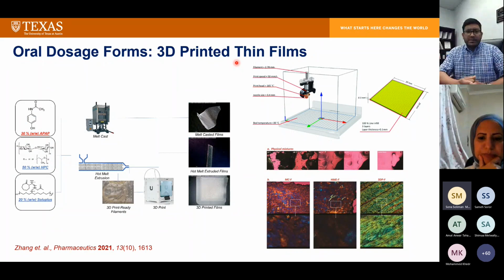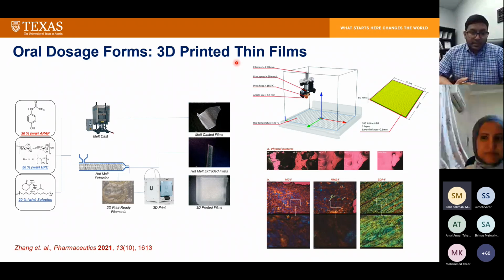So the second case study is about producing 3D printed thin films for personalized application. The reason why we conducted this study was mostly to show the viability of 3D printing for producing thin films, right? So we compared with some other traditionally adopted technologies like melt casting and hot melt extrusion, and of course, we used our 3D printing, just to look at the structure and also the properties and performance.